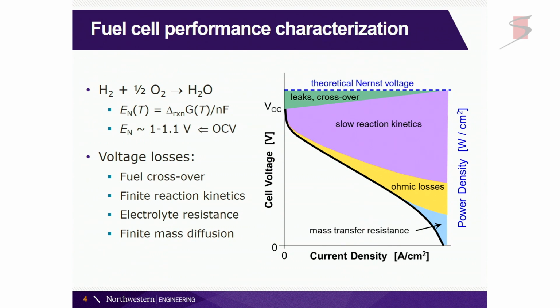And we characterize the fuel cell by what's called the polarization curve, where we look at the voltage as a function of current density. Under open circuit conditions, where we're not drawing any current out of our system, we have a voltage that's essentially determined by the thermodynamics of our system. That'll be on the order of 1 or a little over 1 volt, depending on the temperature we're operating at. This open circuit voltage may often be lower than the Nernst voltage for a number of reasons, even under open circuit, because of perhaps electronic leaks or other sorts of leaks through our membrane itself. And if you're working at high temperatures, as my lab does, the students are always very sad because they have leaks in their seals, and you're not learning much about your material yet.